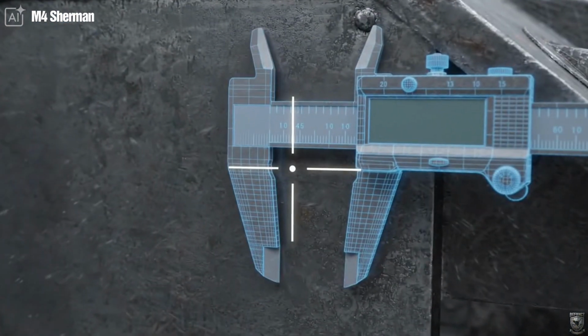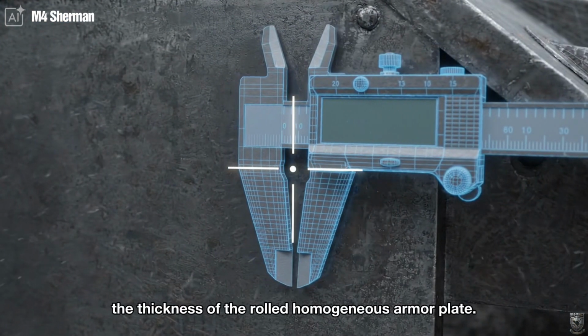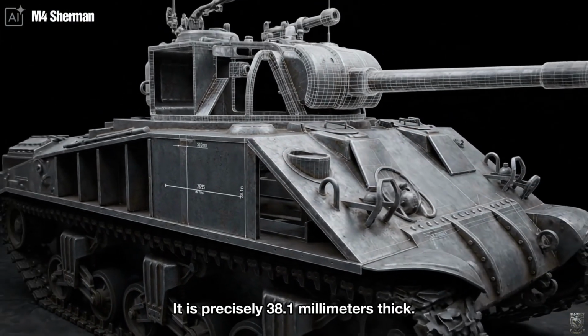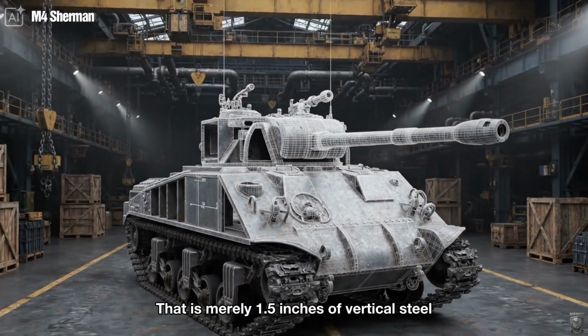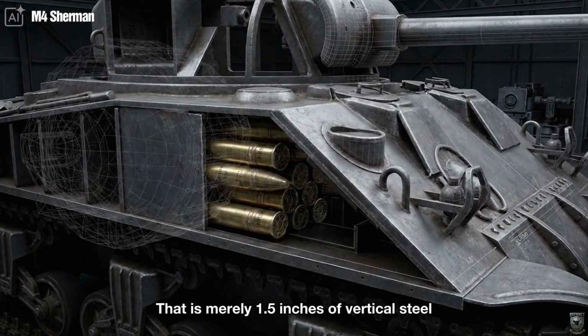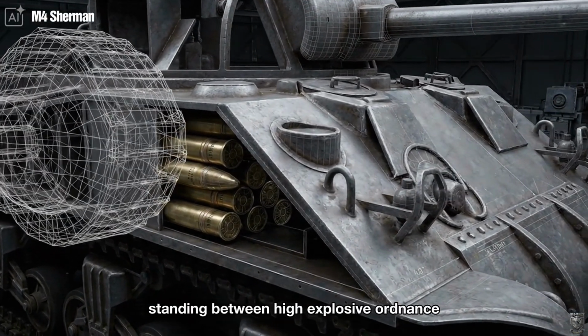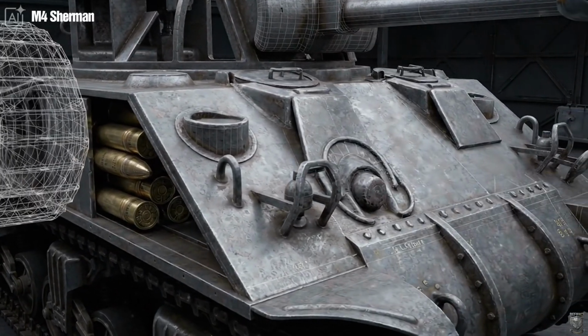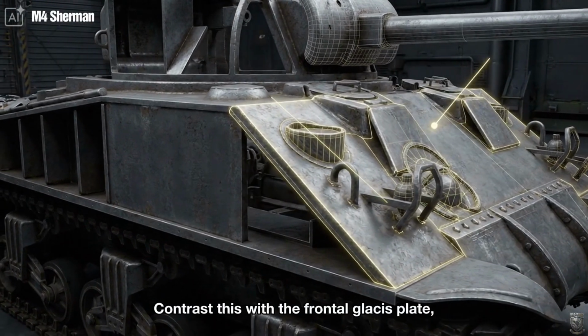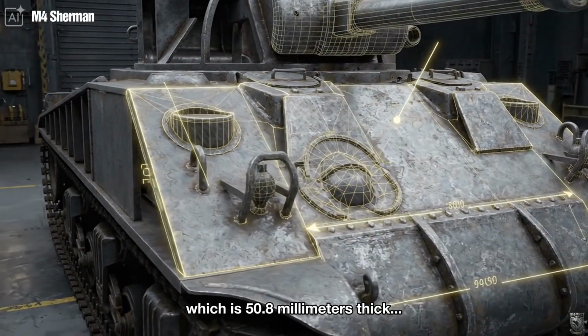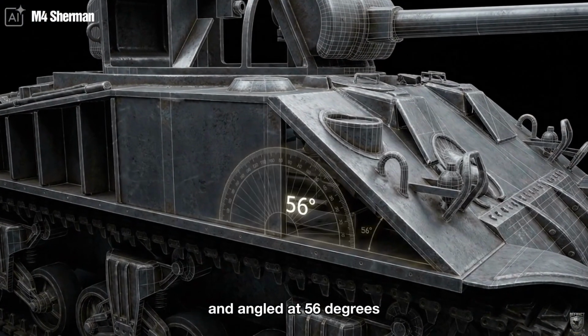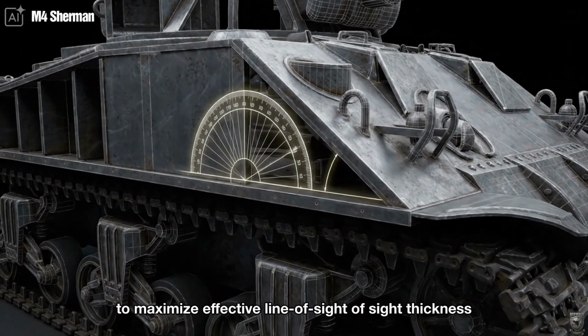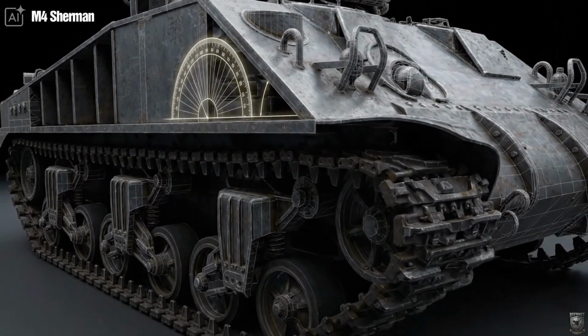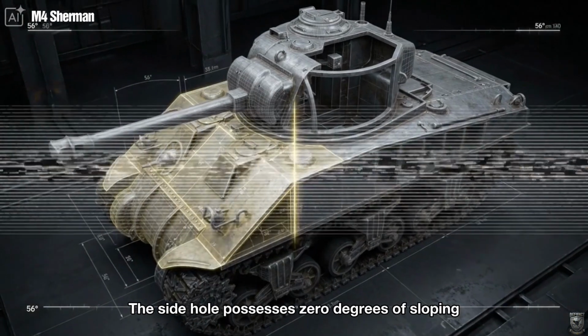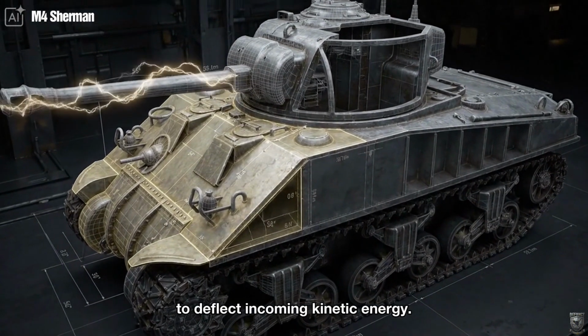Zoom in on the side hull armor protecting these sponson racks. Measure the thickness of the rolled homogeneous armor plate. It is precisely 38.1 millimeters thick. That is merely 1.5 inches of vertical steel, standing between high explosive ordnance and the outside world. Contrast this with the frontal glacis plate, which is 50.8 millimeters thick, and angled at 56 degrees to maximize effective line of sight thickness and induce projectile deflection. The side hull possesses 0 degrees of sloping to deflect incoming kinetic energy.